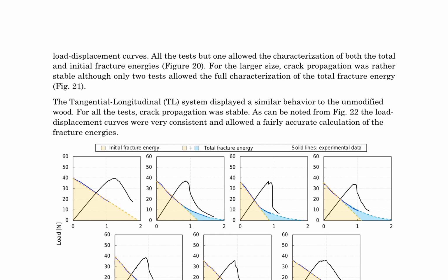calculation of fracture energies. Figure 22 presents the load as a function of vertical displacement for the thermally modified TL system, showcasing shifted load displacement curves and fitted extrapolation functions used to calculate initial and total fracture energies. Table 4 summarizes the fracture energies of thermally modified wood, revealing that the radial-longitudinal (RL) system exhibits a larger fracture energy compared to the TL system, consistent with unmodified wood.